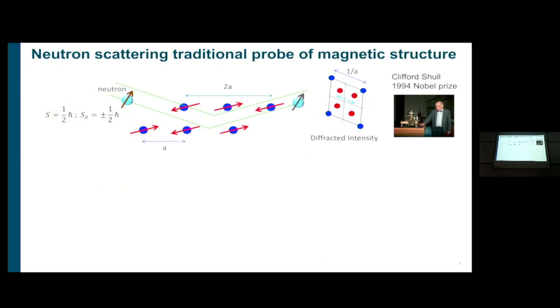So neutrons are the thing that comes to mind when you think about probing magnetic structures, because neutrons have a spin half, and you can polarize them, and the spin of the neutrons directly interacts with the spin of the electrons. So you get very strong magnetic scattering from the electron spin, and you can also probe the lattice structure because the neutron interacts with the nuclei of the atoms. So whether you have antiferromagnetic order, where the periodicity of the magnetic structure is not the same as the lattice periodicity, or whether you have ferromagnetic order where the periodicity of the magnetic structure is the same as that of the lattice, in that case, the magnetic scattering is on top of the lattice or nuclear scattering. And even then, you can see it very clearly in neutrons because the magnetic and the nuclear scattering cross-sections are similar. So Shull won the Nobel Prize for showing that neutrons can be used to probe magnetic structures.